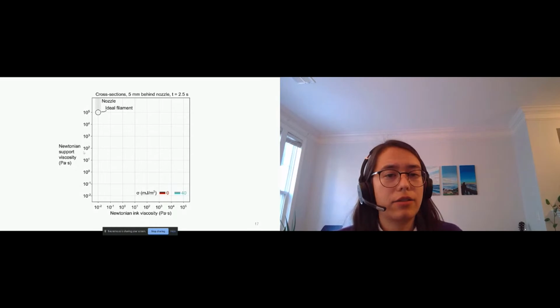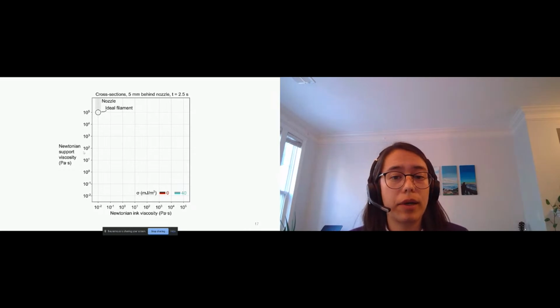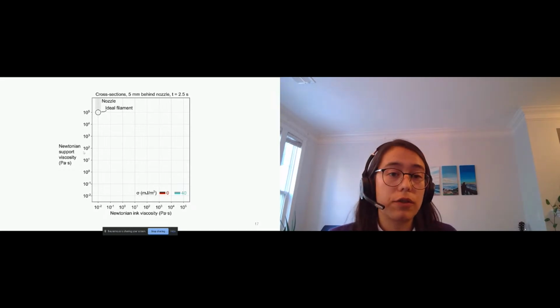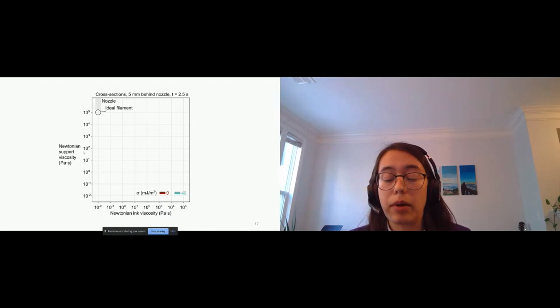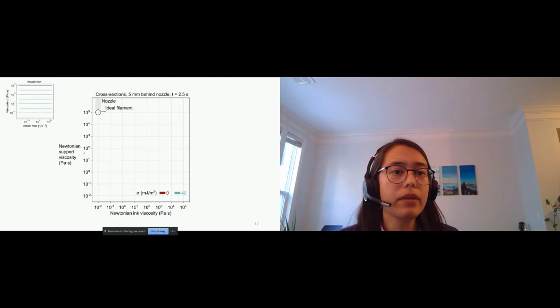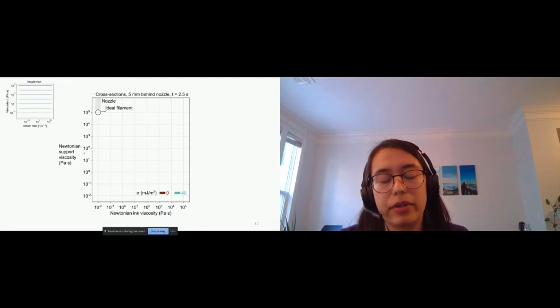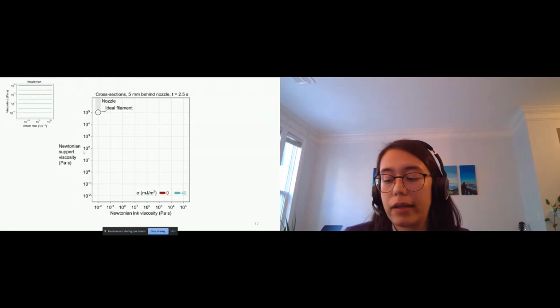We're also going to be looking at a circular shape because if there's any sort of sharp edges on these filaments, that could lead to porosity in the final part, or it could lead to surface roughness, both of which would be problematic. So for these Newtonian fluids, remember this viscosity is going to be constant with strain rate.